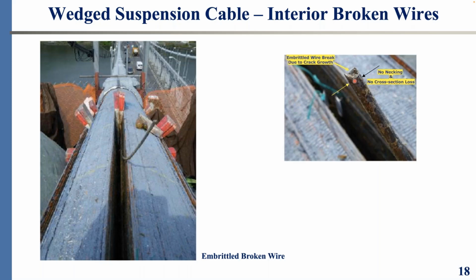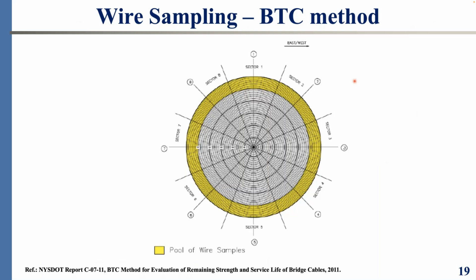We do the wire samples. What you see, this yellow donut, is basically defining what we consider the pool of wire samples. What we say is we do not sample a wire from here. Why not? You told us that some cables have more than 27,000 wires, on average you find cables with 10, 12,000 wires. So how does it hurt to take a sample here and just leave it alone without splicing? Well, the problem with that is you leave a void.